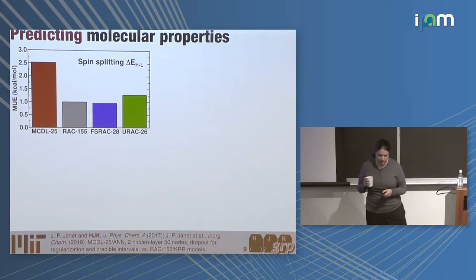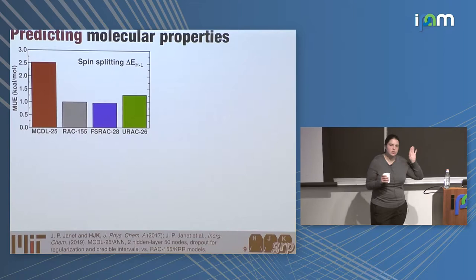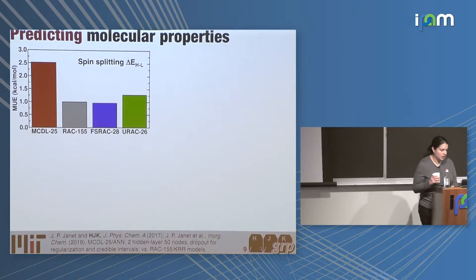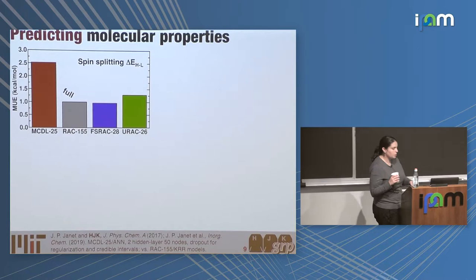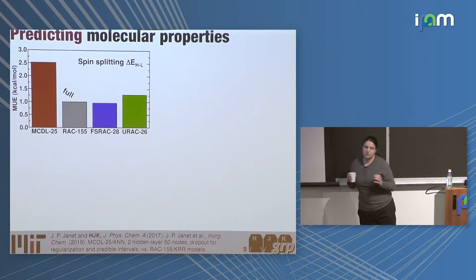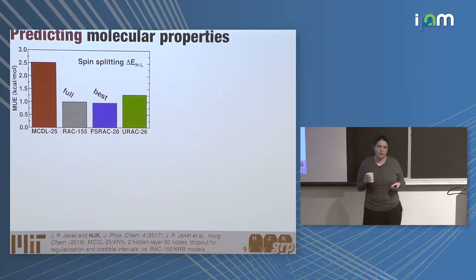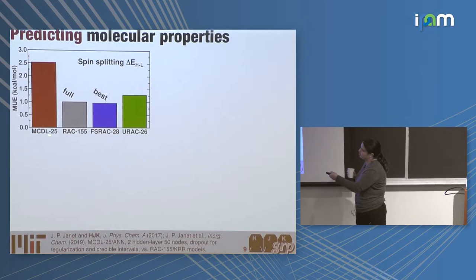We did the representation that was my idea as the domain expert, and then we developed a more systematic approach that could expand to include features I had selected but also others I wouldn't have known about. What you can see is that you can achieve sub-kilocalorie-per-mole accuracy on predicting the quantum mechanical ground state spin with the improved features — a significant reduction in error from the ad hoc representation. You might think that's just because of the increase in number of dimensions allowing better fitting. But it turns out that if you apply feature selection and identify the most essential features, you can get the feature set down to about the same dimension as MCDL-25 without loss in accuracy.